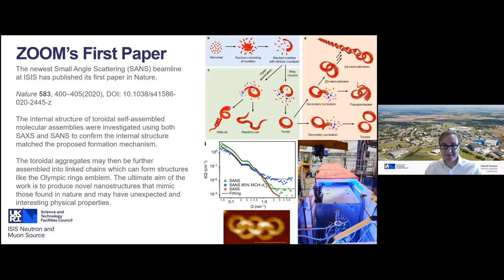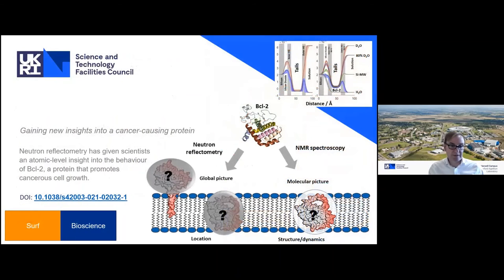But of course, this is just microscopy. This is atomic force microscopy that shows you this image. So it's very nice. But what neutrons allow you to do, with some modeling, is to not only see the structure, but also to see inside the structure. And so each of these has a little kind of structure, which is a so-called core shell model. And we can see inside that, we can see the interpenetration of the solvent molecules and so on, which you can't get from other techniques. And actually looking inside materials is clearly a big part of what we do.